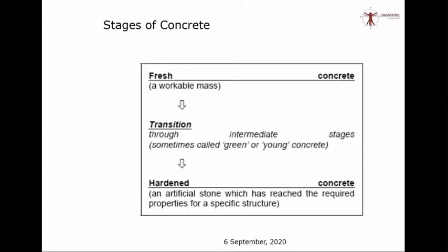In the first stage, we all would have done the slump cone test. You know how fresh concrete looks. You know how to do the slump cone, where at the first stage, the most important parameter viewed for concrete is the workability. In the hardened stage, the most important parameter is mostly the compressive strength. In some special structures, we also look at the tensile strength of concrete, the crack pattern, the crack width, etc. But coming to this transition stage, what is this transition stage?